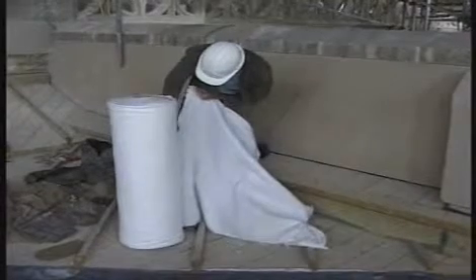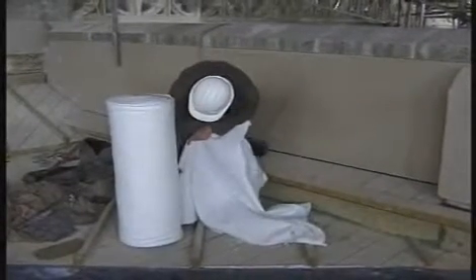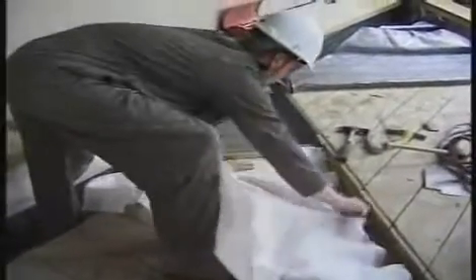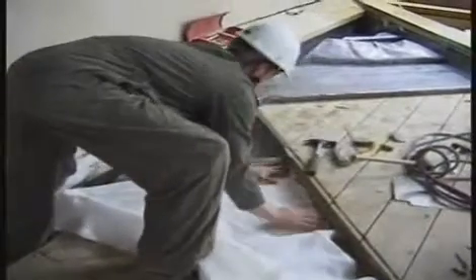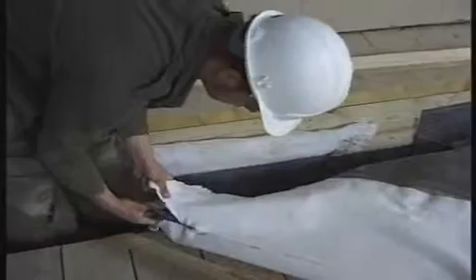The slip layer here is a synthetic textile made from polyester. This comparatively recent material has replaced slip layers made from bitumen felt. In hot weather, the bitumen could melt and stick to the lead and deck. This bonding restricted thermal movement. The impervious felt also restricted the evaporation of any condensation which might have occurred underneath the lead.